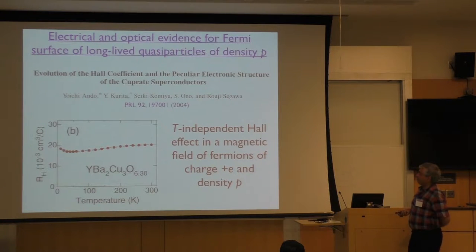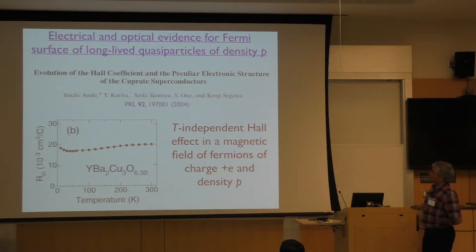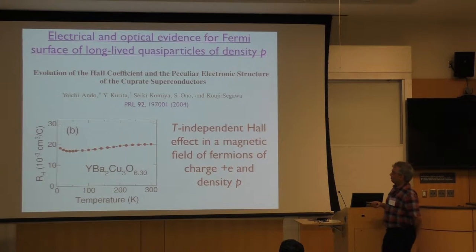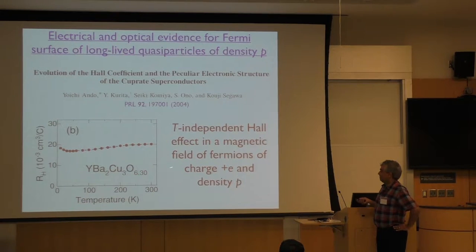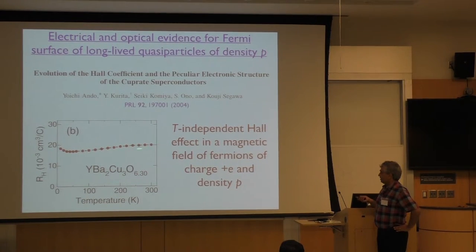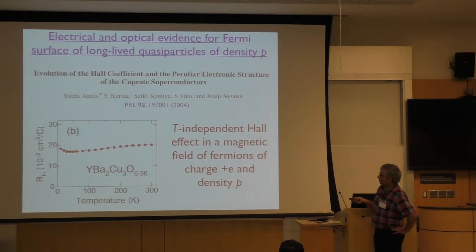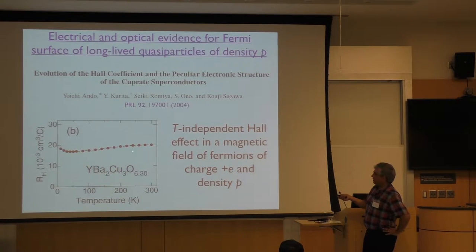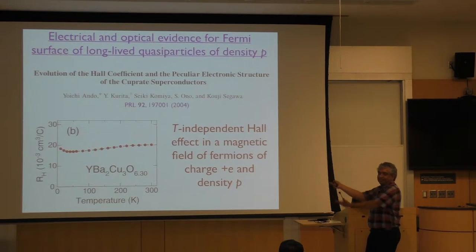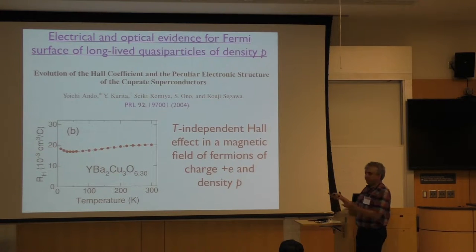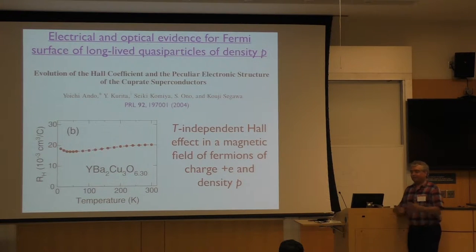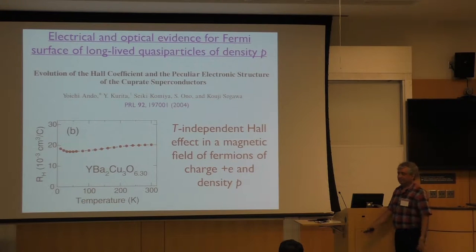One idea of the simplicity goes back to a measurement a few years ago of the Hall coefficient in the pseudo-gap regime. What you find even at high temperatures is a temperature-independent Hall coefficient of density plus P. So if I just told you: here's a metal which has density P of holes — you would say yes, of course, there's a metal of density P of holes, Hall coefficient temperature-independent.